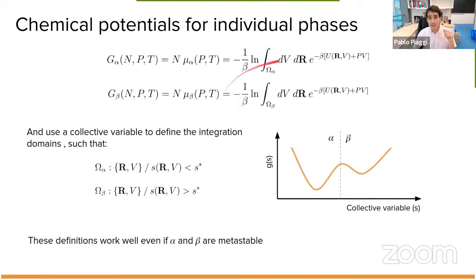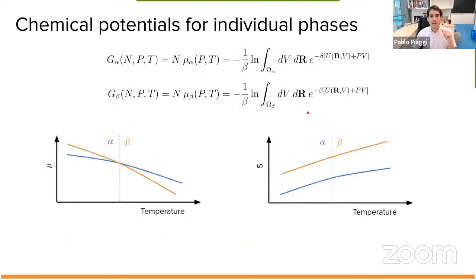Importantly, these definitions, the ones that I wrote here, that we're going to use, work well even if alpha and beta are metastable. And to make some connections with thermodynamics of materials and the plots that one typically sees in books of thermodynamics of materials, what I'm showing here is the chemical potential as a function of temperature. And you see that below some transition temperature, alpha is more stable, and above the transition temperature, beta becomes more stable.